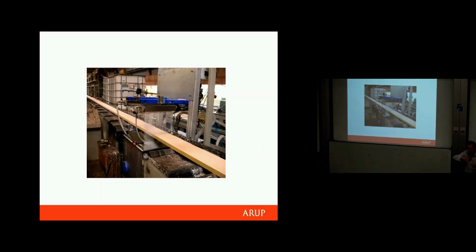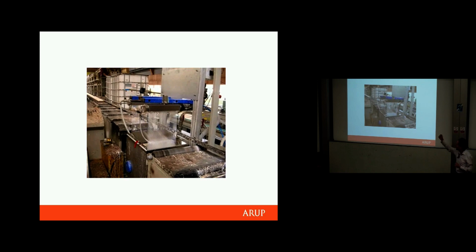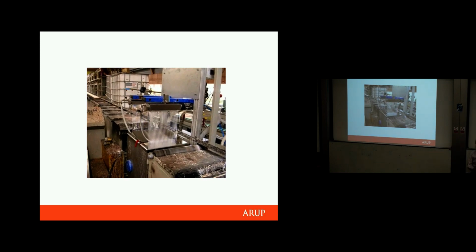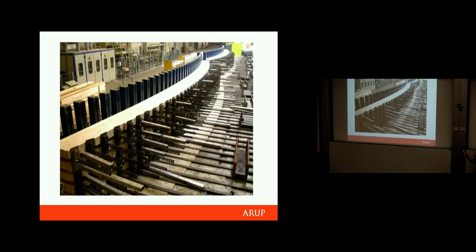and then we've got our long planks, we pass them through what's called a glue curtain. You can see there are actually 2 curtains. This one is the resin, and the second one is the hardener. So the idea is that the resin and the hardener mix on the surface of the wood. And then we simply stack up the planks and clamp them together overnight until the glue has cured. You can play with the curing time, but normally we work with about an 8-hour or so curing time.